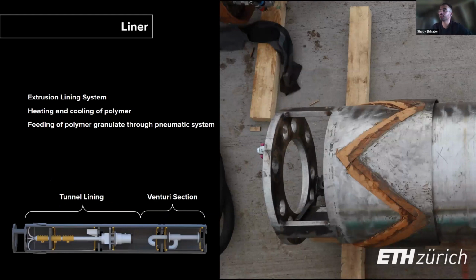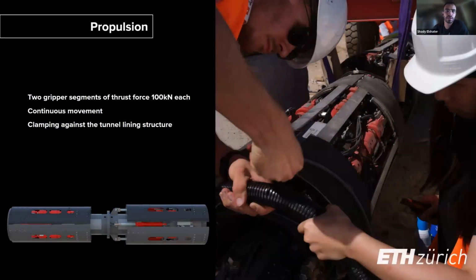Then the liner, so this extrusion lining system, we first heat a polymer and then we cool it down, and we feed the polymer granulate through a pneumatic system. But more details about the liner afterwards. So for the propulsion, as I said, 2 gripper plates, 100 kilonewton each, so up to 200 kilonewton in total. Continuous movement, and we developed several kinds of controllers. We have simple open loop controllers up to more advanced model predictive controllers.